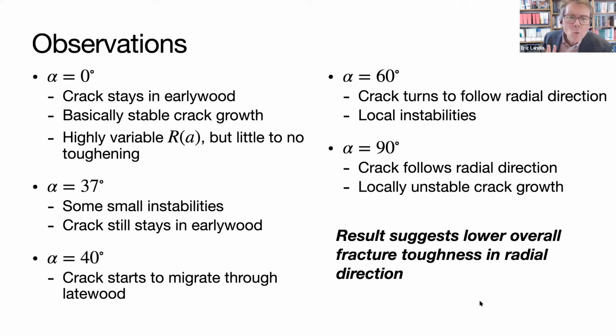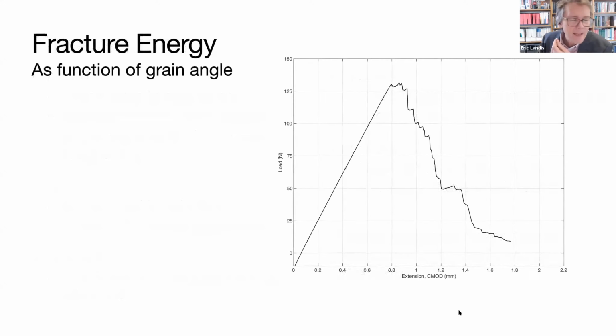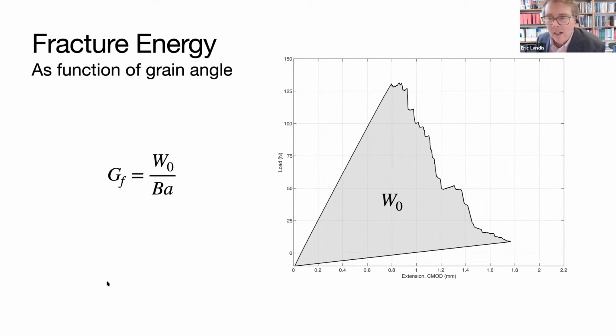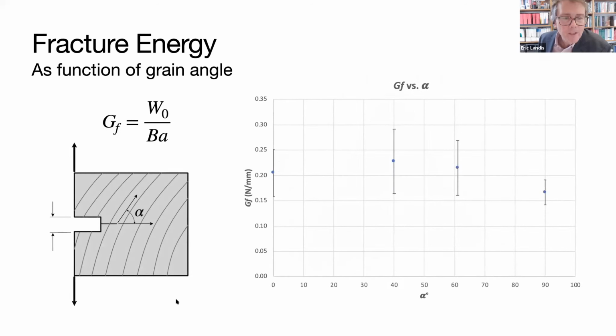And to test this in another way, we took our data and then, dusting off my fracture mechanics of concrete, we just looked at overall fracture energy. So we take the energy, we basically load the specimen out as far as we can, get the area under the curve, and divide that by the change in crack area. And plot that for different angles. And of course, statistical significance may be a problem, but the trend we see, whether we want to see it or not, is an increase and then a decrease. So in fact, the radial direction, which is represented out here, is lower.